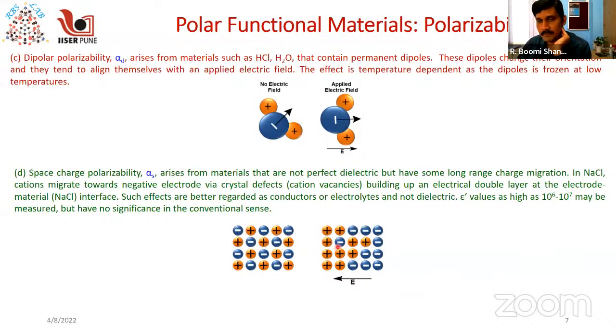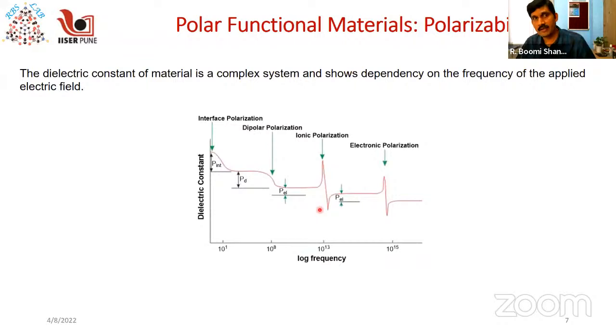As a result, these molecules will show an enormous dielectric constant under the electric field. However, if you perform this experiment at higher frequencies of the electric field application, the migrated charges will go back to their original state and remove the enormous dipole moment that is produced in the system. That means that if you want to get rid of the space charge polarization, you have to perform this experiment at higher frequencies. Which brings me to the next slide: the dielectric constant of the material is therefore dependent on the frequency of the applied electric field.